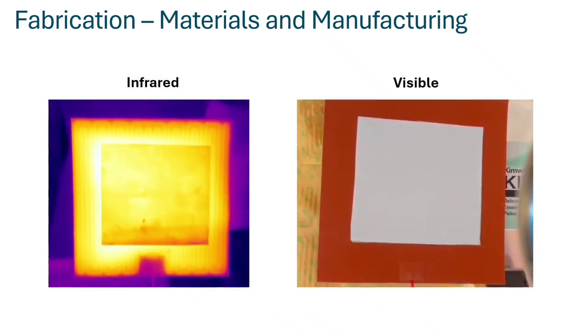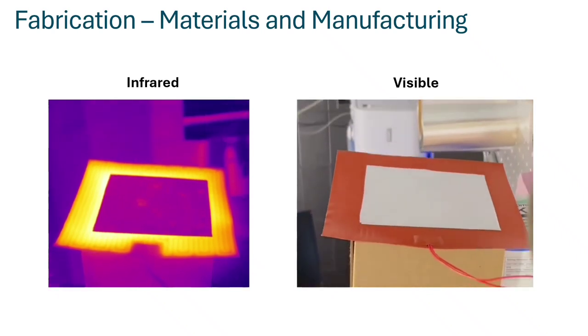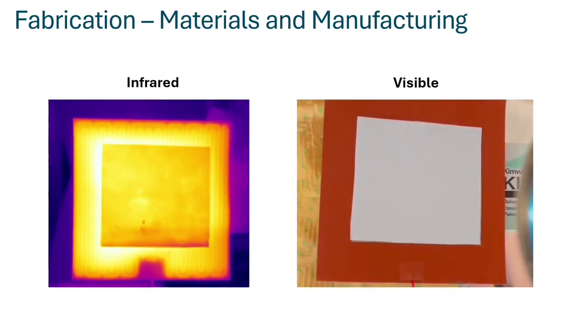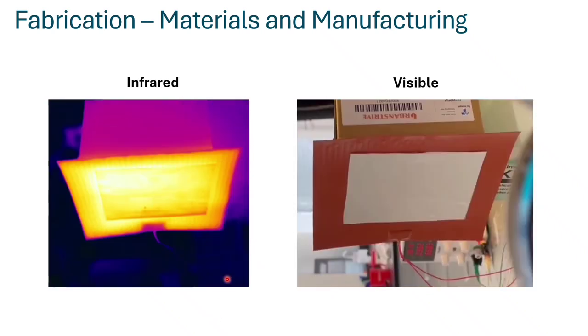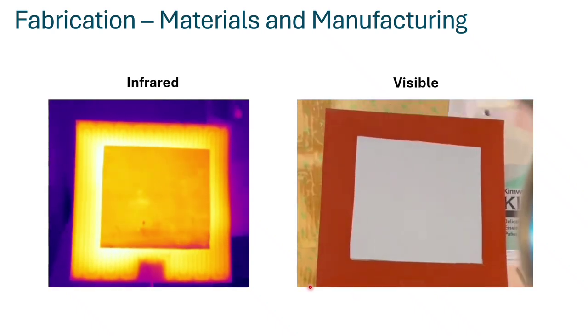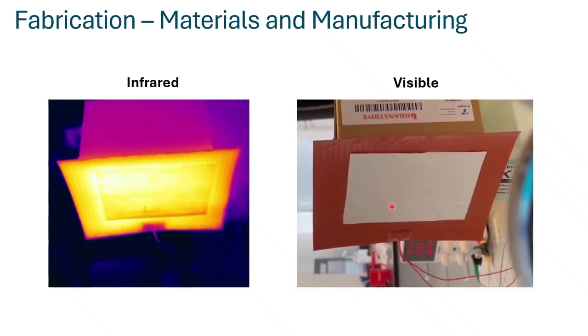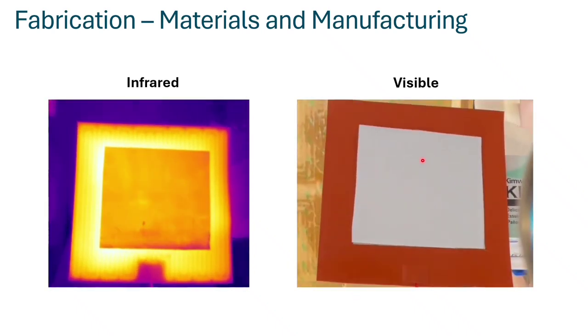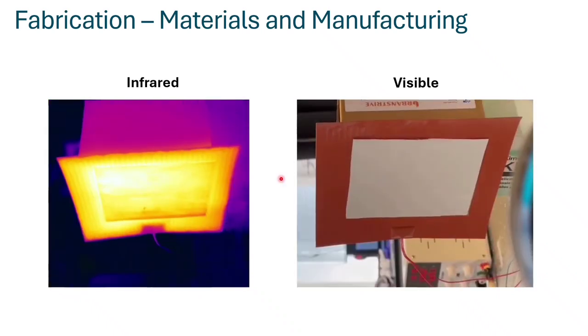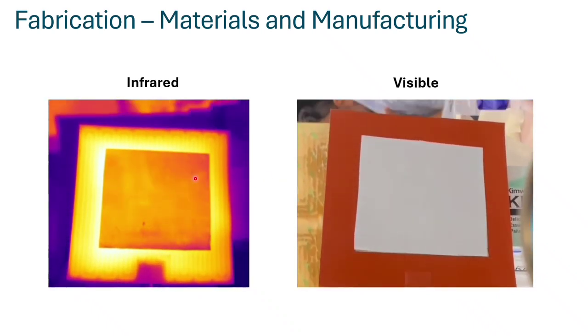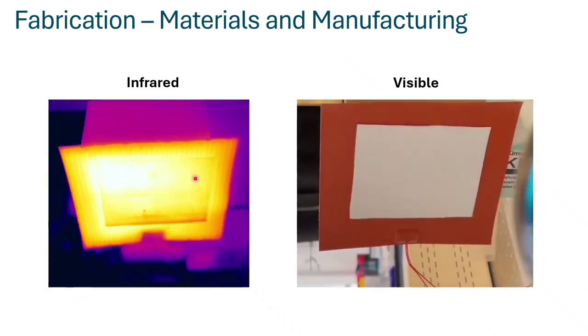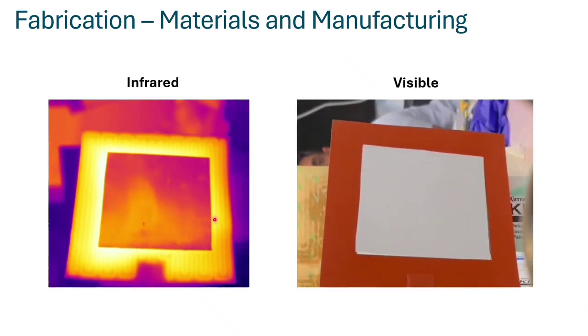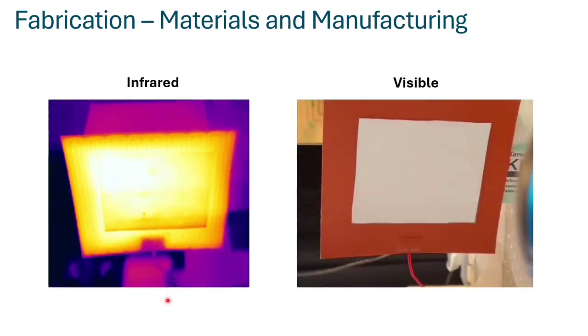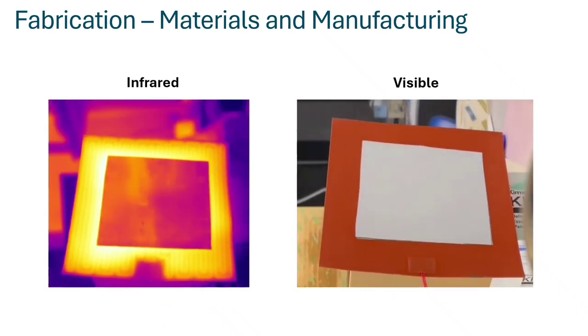Here, the directional emitter is shown at the viewing angles that sweep from above to below the horizon, imaged with a thermal camera on the left and in the visible on the right. We note an omnidirectional constant white appearance in the visible, while in the infrared you can clearly see the transition. Above the horizon, the emitter is bright with high radiance and emittance, but now below the horizon, it becomes dim, exhibiting low radiance and low emittance.